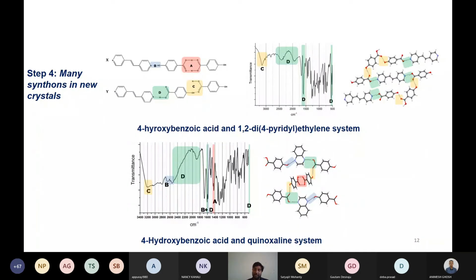And an even more interesting case happened in the next example, which is 4-hydroxybenzoic acid and quinoxaline. When we tried to make this powder, we observed all 4 synthons. And we thought it could be a mixture, but then to make more sense of this result, we did the single crystal analysis, and surprisingly, it's not a synthon polymorph, but all 4 synthons did exist in the same crystal structure.